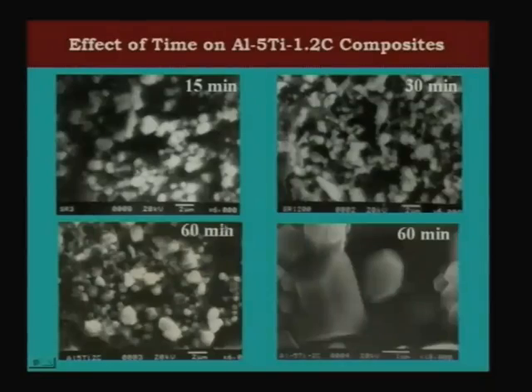So, if you do that, this is as a function of reaction time. Again here also you need a minimum of about 60 minutes for the reaction to give you a more or less uniform distribution of particles, and these particles are of faceted nature, and this faceted nature is very useful when you want to use them as grain refiners also, because TiC is cubic in nature, TiC can also act not only as an aluminum TiC composite, but also as a grain refiner. One can use the aluminum TiC as a grain refiner for aluminum alloys. We will come to it a little later.